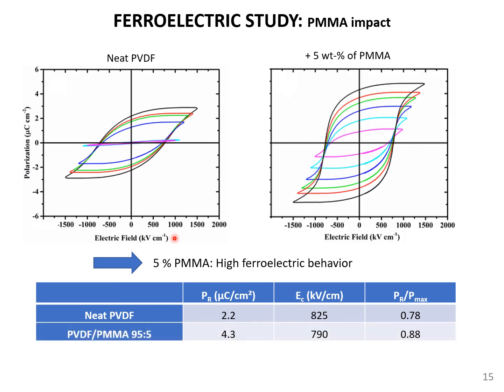When you add 5% of PMMA, you can improve the remnant polarization, passing from 2 to 4. And also you have a decrease of the coercitive electric field. In other terms, you improve the pooling process using this PMMA.